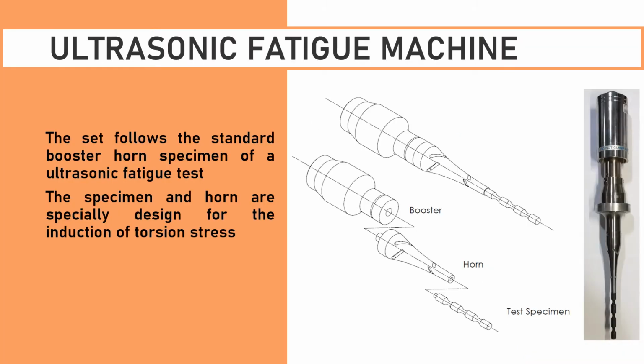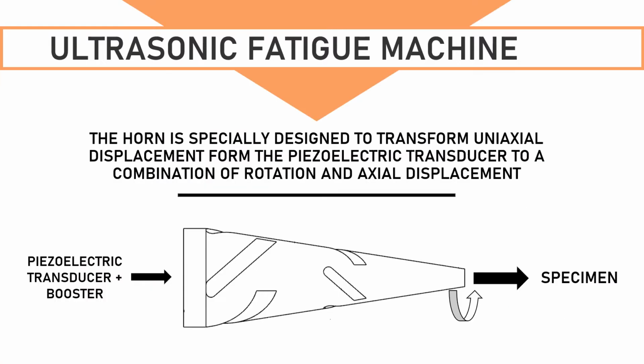So the ultrasonic fatigue machine we use is very similar to a standard uniaxial fatigue test that we also performed. It is composed of a booster, horn, and a test specimen, and they are excited by a transducer. On the right, you'll see the image of the testing machine. The specimen and the horn are the ones that have special design to create the tension torsion stress state.